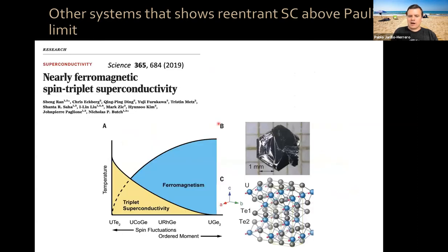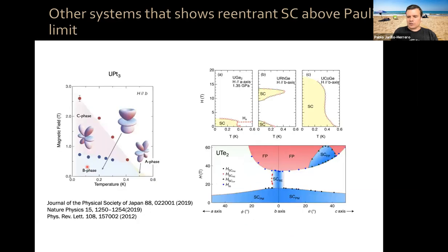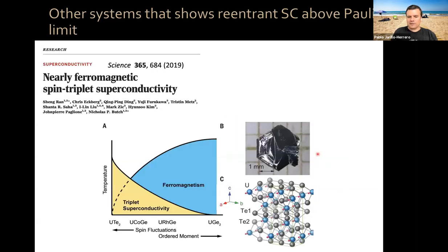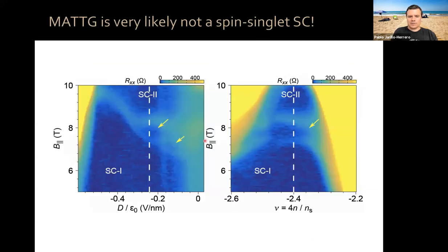These superconductors are either ferromagnetic superconductors, or, in the case of uranium Te2, it is at the critical point here, where it is a spin triplet, nearly ferromagnetic, but not actually ferromagnetic superconductor. Okay. And they see this transition to a field polarized phase at high field. We also see these transitions at a certain magnetic field, okay, that separates superconducting one and superconducting two regions. Okay. We sometimes see maybe even some signs of other phases, but here resistivity doesn't go precisely to zero. So we don't know if those are really true phases.